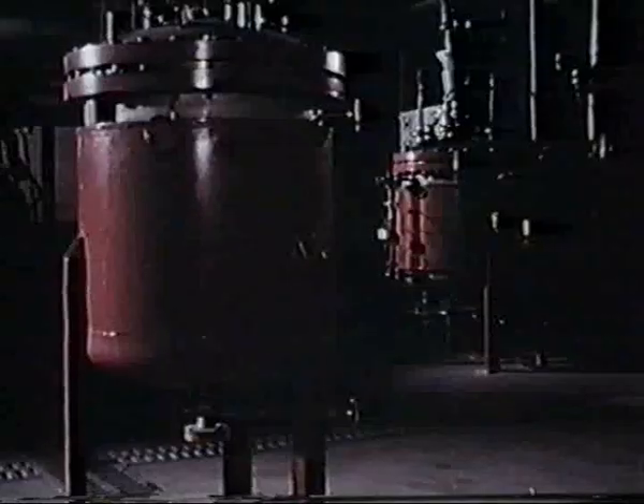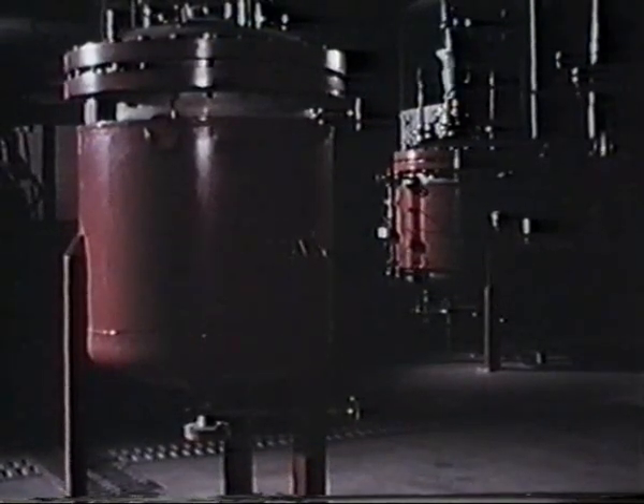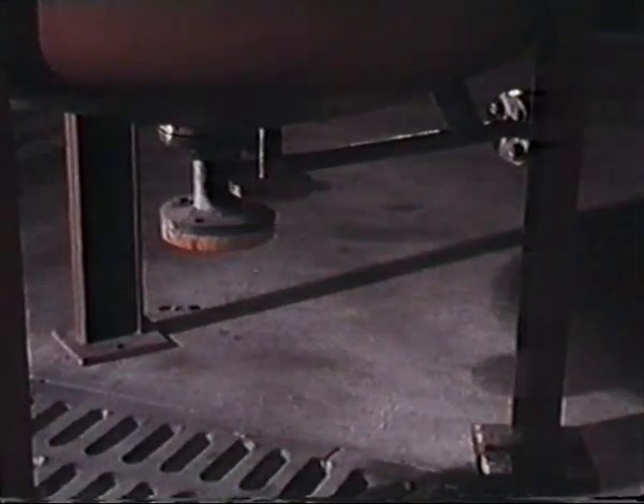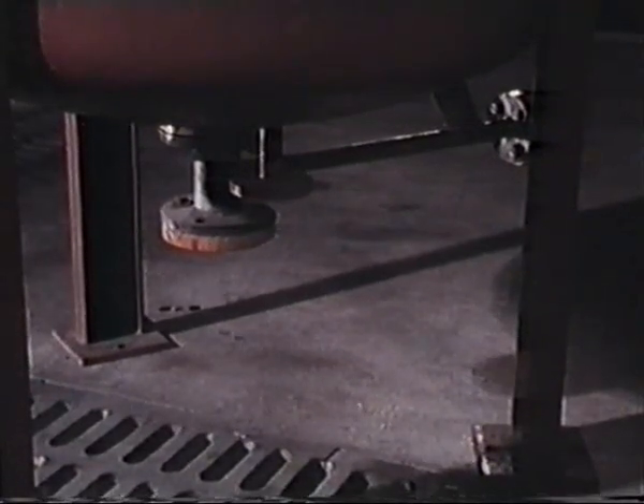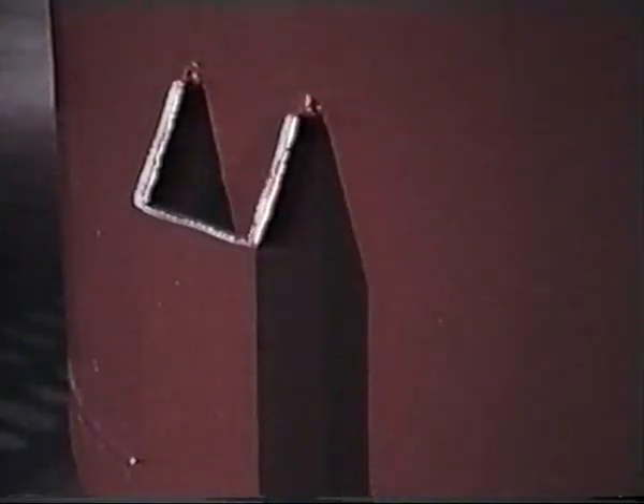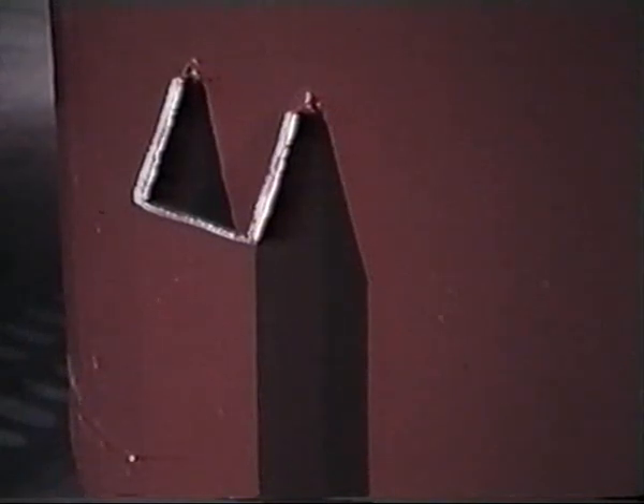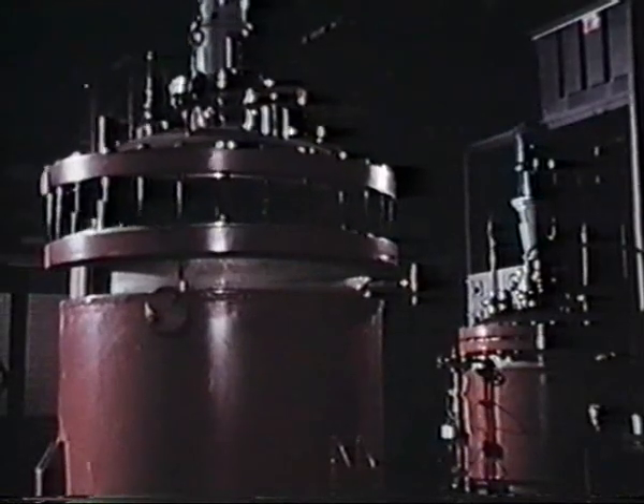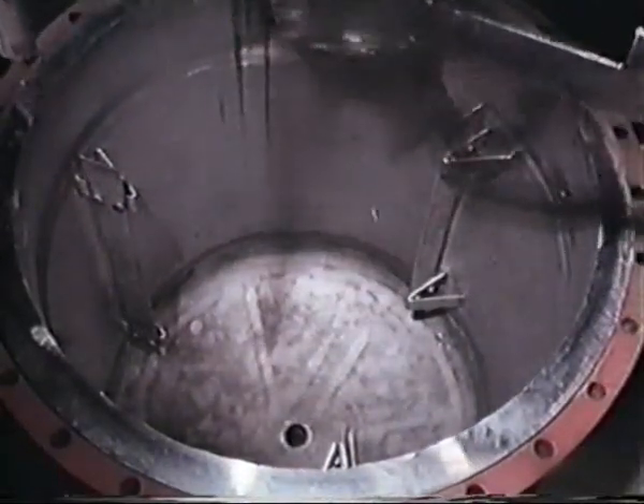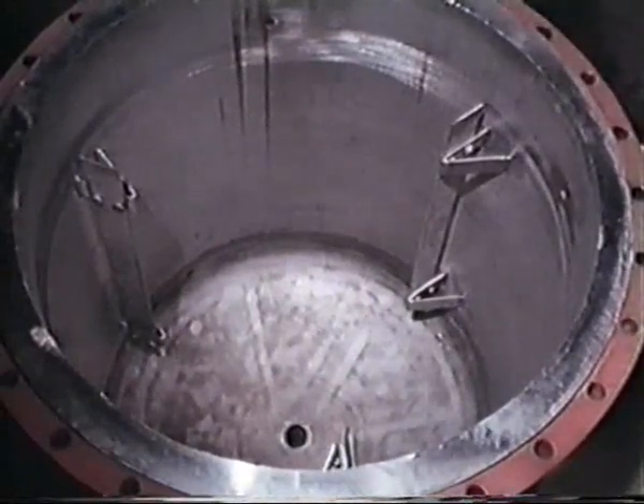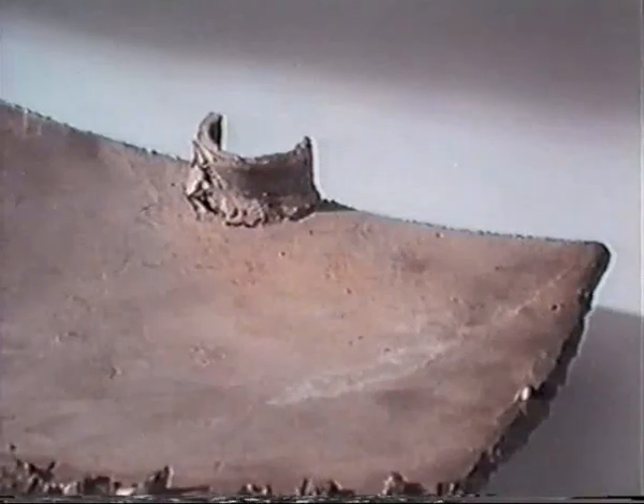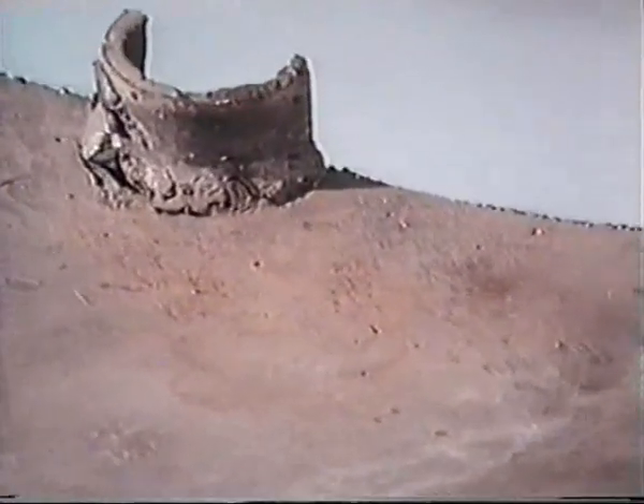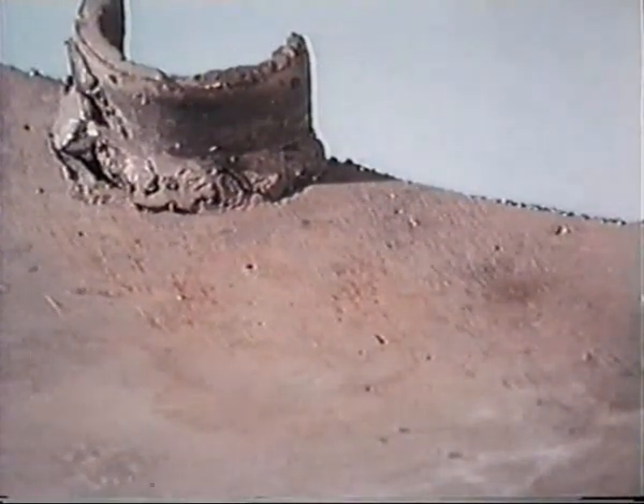Corrosion can occur both on the inside and on the outside of a vessel. Exterior shape can also prevent corrosion. When lifted well off ground, the underside is accessible for maintenance and painting. Good design of legs eliminates trapped water in crevices and facilitates cleaning. Inside, an outlet pipe at the bottom and machined flush gives the essential complete drainage. As we have seen, if the outlet is not flush, corrosion can occur. The liquid left between process cycles, concentrated by evaporation, then attacked the weld and caused pitting of the bottom of the vessel. A minor fault in design can shut down a large and costly operation through corrosion.